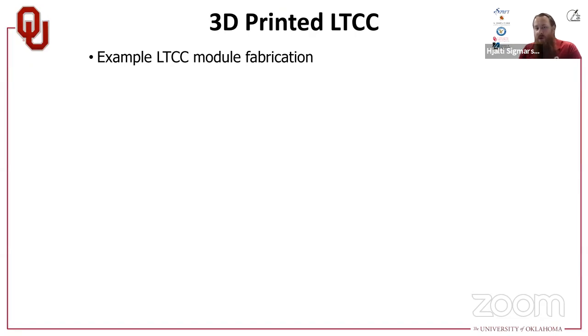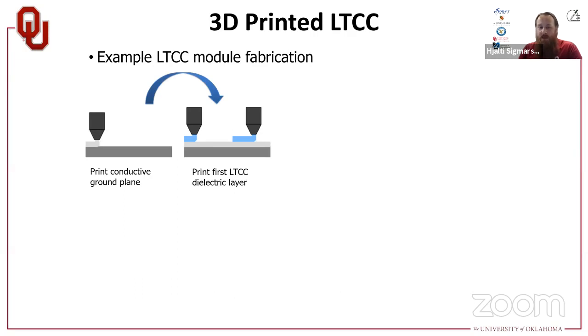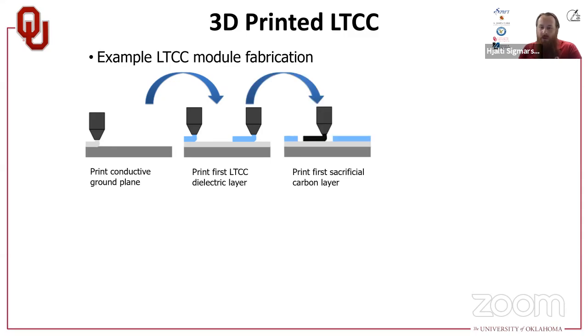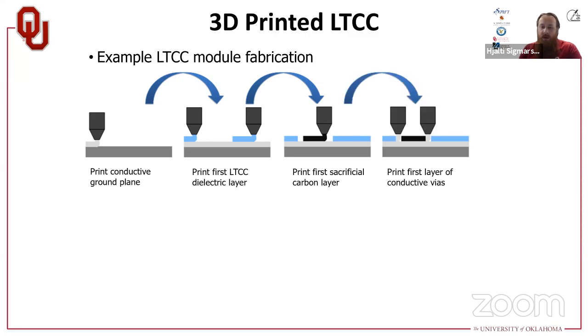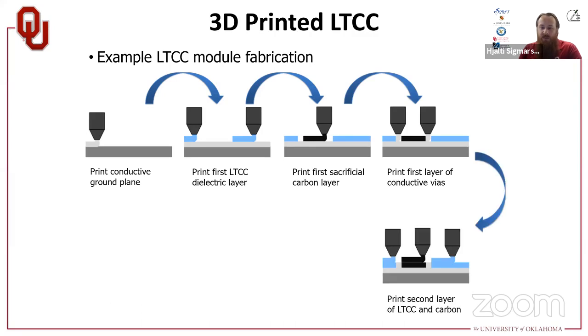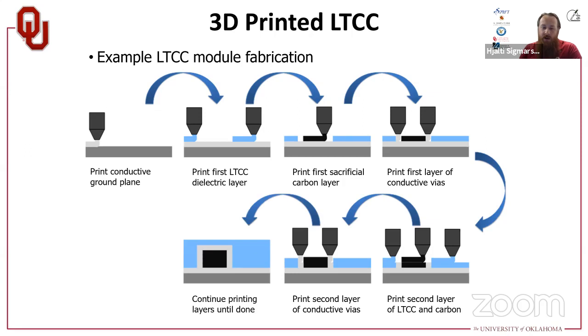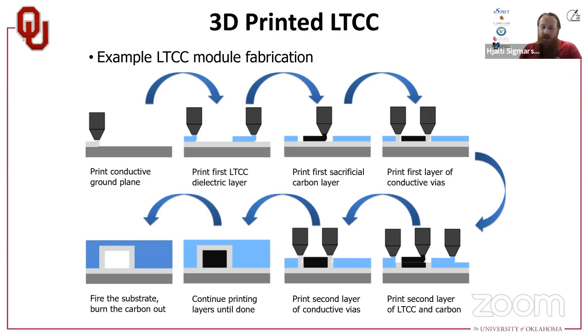So how do we envision doing this module fabrication? If we start off with just printing a ground plane, for example. We're assuming that we're building some kind of circuit. So we start with printing our layers, maybe print a conductor layer, and then we would print some ceramic on top of that, some LTCC. Here's an example where we would put down a sacrificial carbon layer if we want to create some cavities or channels. So we would print some carbon in there, and we continue filling some vias, and then that repeats itself. We just keep building on top of that layer by layer until we end up with a complete part. Then eventually we fire that part, and during the firing process, the purpose of the carbon paste is that it actually does get burnt out quite nicely.